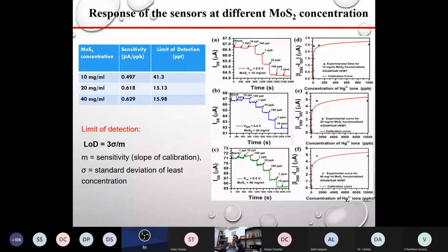Another question is how much MoS2 quantity we have to transfer. So we have used different concentrations: 10 mg per milliliter, 20 mg per milliliter, and 40 mg per milliliter. We found that initially it is increasing, but 20 milligram per milliliter is the maximum where we got the best sensitivity, and the detection limit is also the minimum. When we increase further, there is not much improvement. Here you can see the data at different concentrations of MoS2 when we are loading on the gate. So almost we got similar behavior.